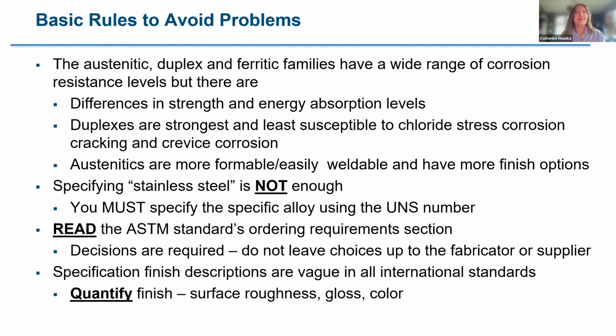So, some basic rules to avoid problems. The three families of stainless steel that I'm going to mention today, which are most commonly used, are austenitic, duplex, and ferritic families. The differences between them are their microstructures, but there are also differences in strength and their ability to absorb energy. Additionally, some of these stainless steels, like the duplexes, are far more resistant to chloride stress corrosion cracking and crevice corrosion. So if you know that that's a potential issue and you can't avoid it, then you might want to consider a duplex over an austenitic.